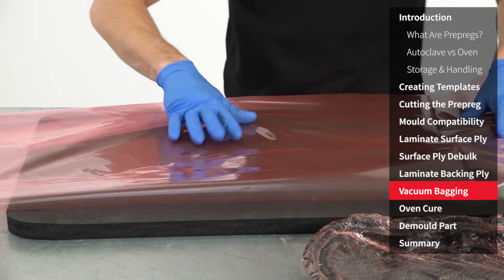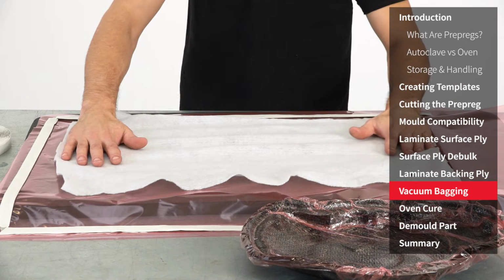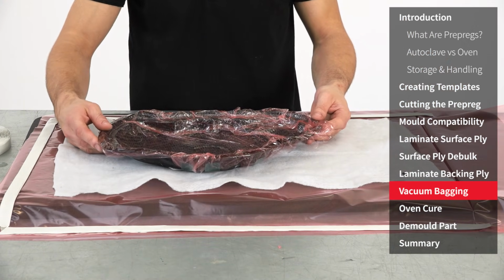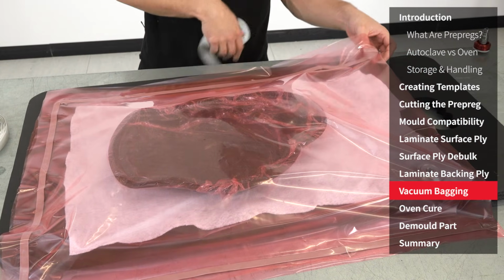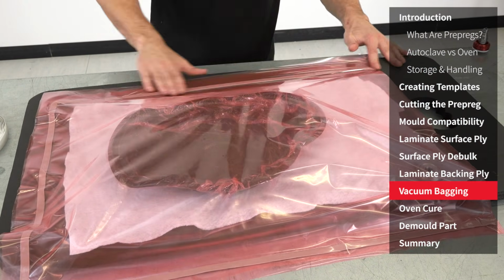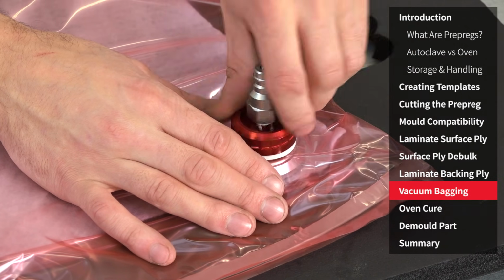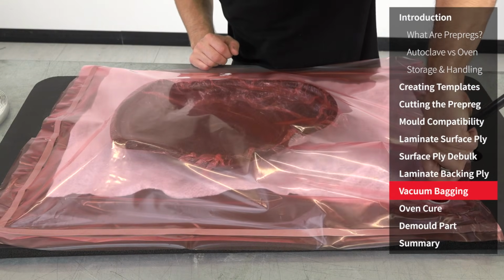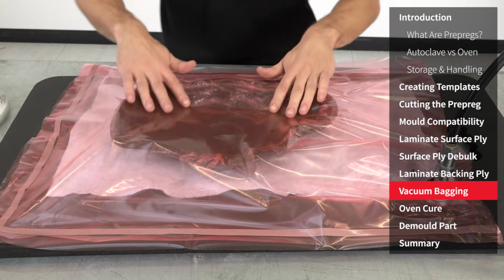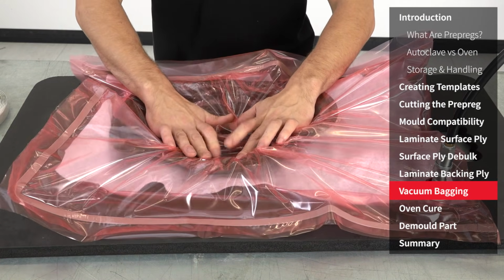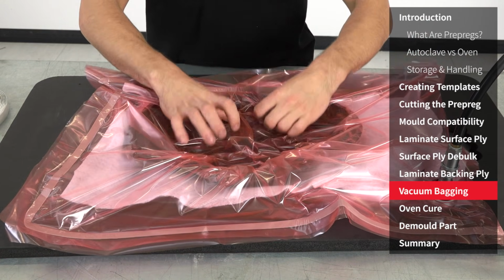As this is a small component, I'm going to put it into an envelope bag. In fact, it's very common to put multiple smaller parts into one large bag. For thin, intricate laminates like this, best results are achieved by using the breather only on the reverse of the mould. This provides the air path needed to the edge of the release film, but means that the film can get into all of the details without the breather getting in the way.